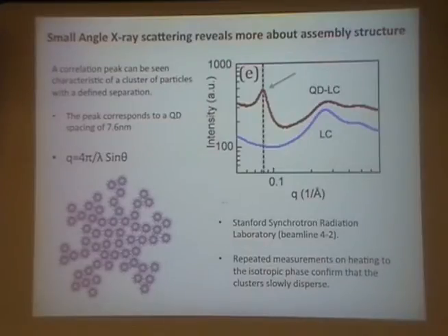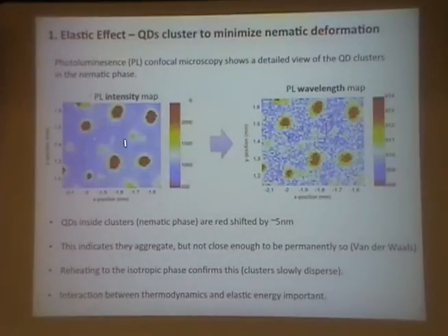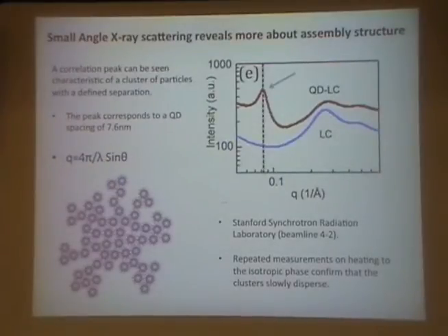Okay, now we had a good introduction on X-ray. I can just show you my results from an X-ray experiment where we did some scattering on these particles in the liquid crystal. In this experiment, we wanted to look at the structure of the clusters. We have these in a capillary, filled with liquid crystal with the clusters inside. We wanted to know what the structure of the clusters is. We can get information from the redshift to tell us the average distance between particles, but we can also do a complementary X-ray experiment.